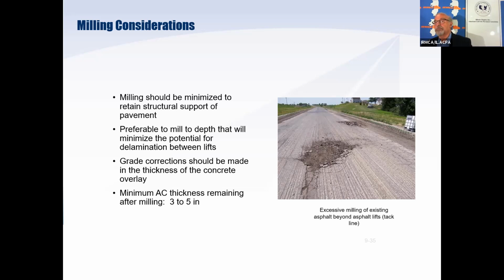So if this is one small area, the rest of the pavement I've cored out and I figure I'm okay, but this one area was very thin. I can come out and I can take a backhoe and I can dig out that specific area, and I can put in asphalt and roll it out. I can put in flowable fill. I can also put in concrete, a lower quality concrete, and strike it off with the surface. And then when I put my overlay, I have uniform thickness and more or less uniform level of support.